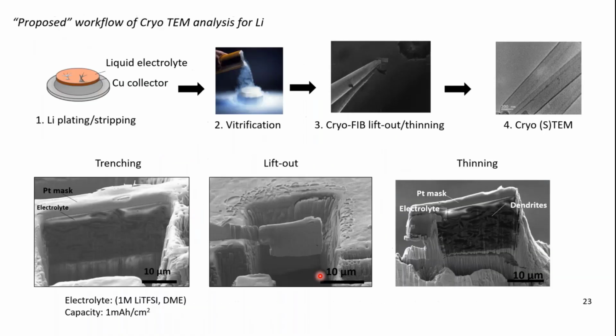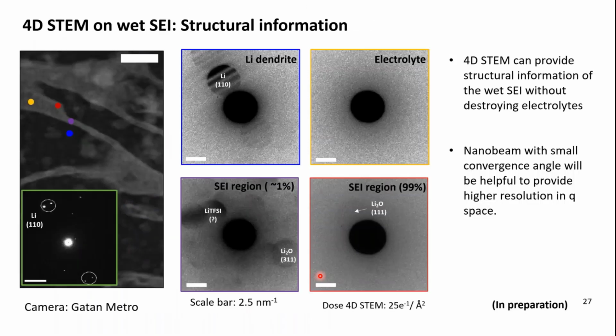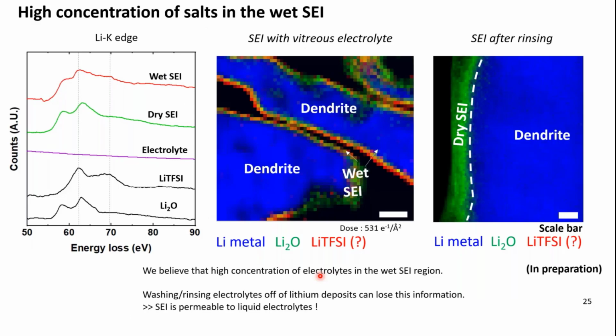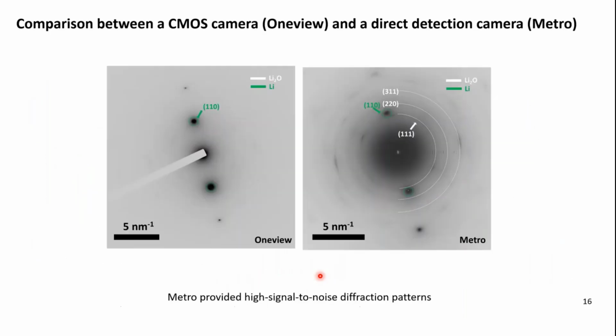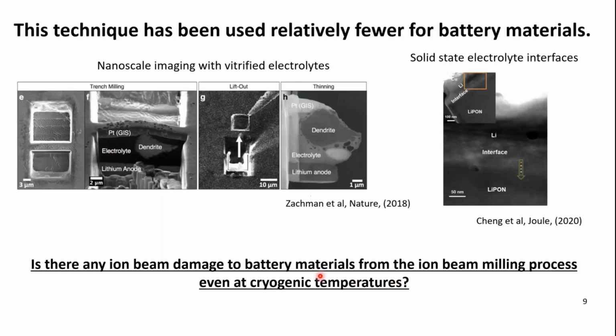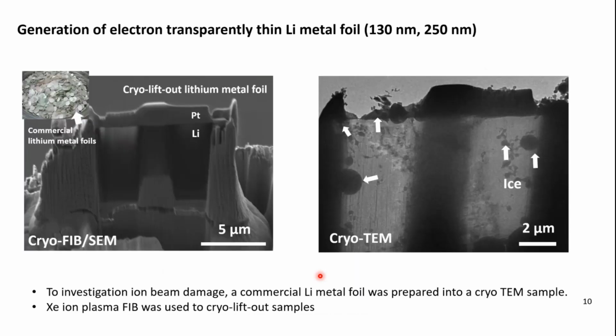Another thing is there has been really nice work from a UC San Diego group on characterization of solid electrolytes, working on the solid electrolyte battery using these cryogenic lift-out procedures. I believe solid electrolyte is one of the best ways to look at the interface, because the interface is pretty well defined between the solid electrolyte and lithium metal, unlike organic electrolyte, where there are too many interfaces at the SEI level. So I would say solid electrolyte would definitely be the best way to characterize in this workflow.